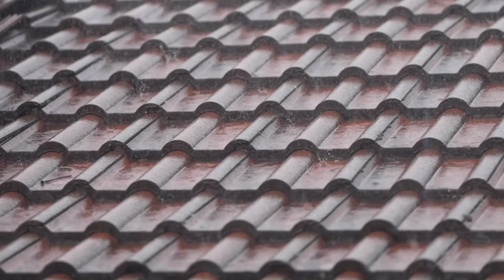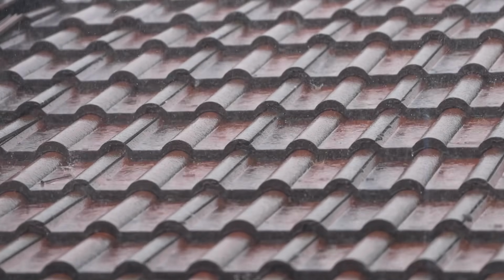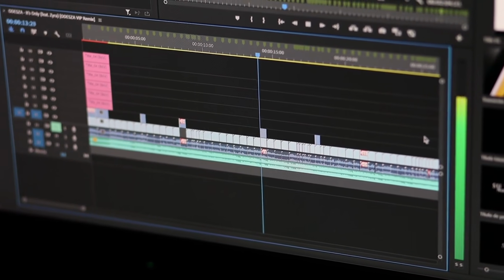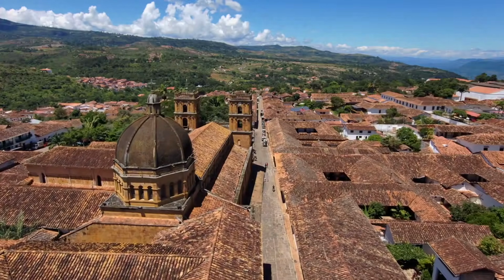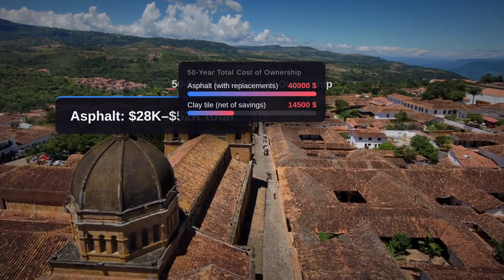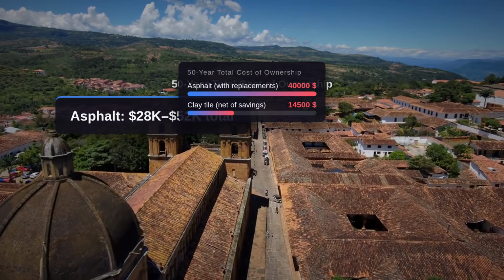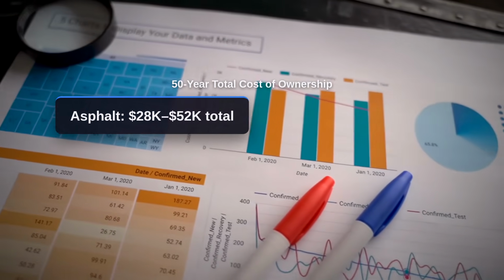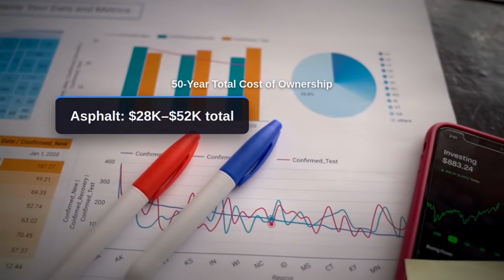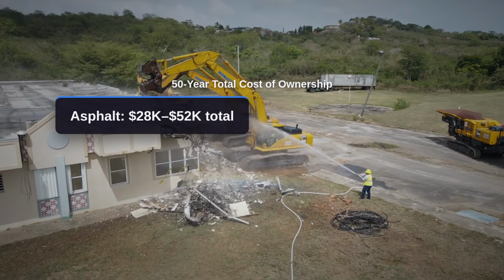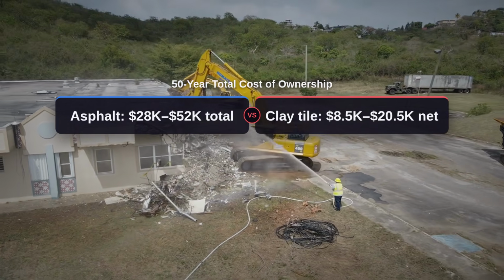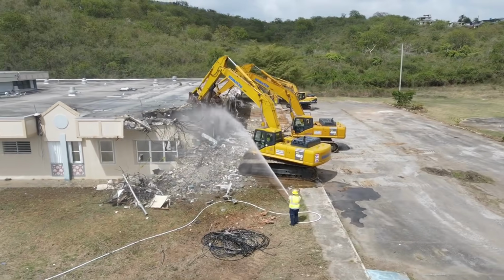So over a 50-year period, you are not comparing one asphalt installation to one clay installation. You are comparing one clay installation to 2 or 3 asphalt replacements, each with its own labor and material costs. A fair 50-year total cost of ownership for asphalt, accounting for 1 or 2 re-roofings, disposal fees, and lost cooling savings, runs $28,000 to $52,000 in today's dollars for a typical home. The clay tile system, including the cooling savings, comes in at $18,000 to $35,000, minus $9,500 to $14,500 in energy savings, netting out to $8,500 to $20,500.